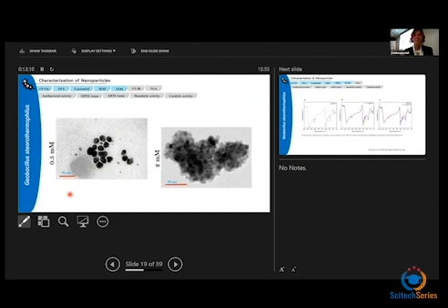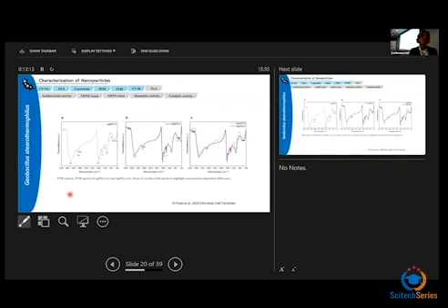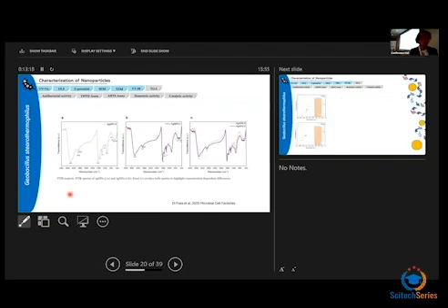We also made some FTIR analysis to try to investigate the surface chemistry and interactions of the silver nanoparticles. As can be seen from the spectra overlaid from the 0.5 and 2 millimolar nanoparticles, in the aliphatic region some differences can be noted, which indicate variations in the organic molecules adsorbed on the nanoparticle surfaces. This better defined peak in the 0.5 millimolar suggests a more ordered and structured organic coating in comparison to the 2 millimolar ones.